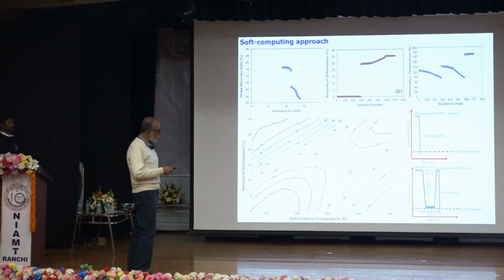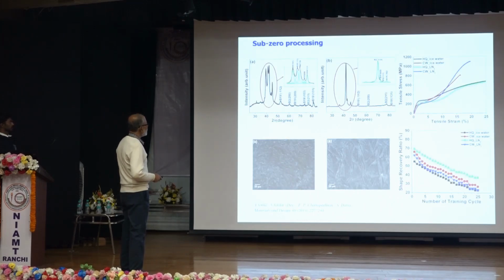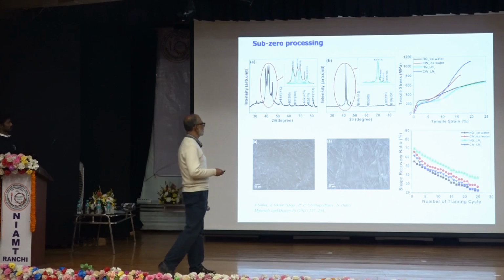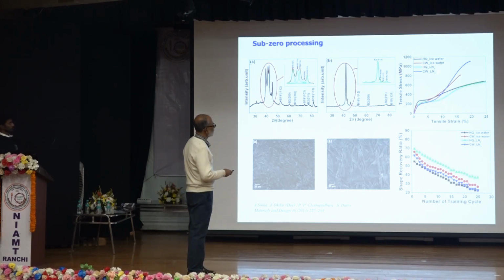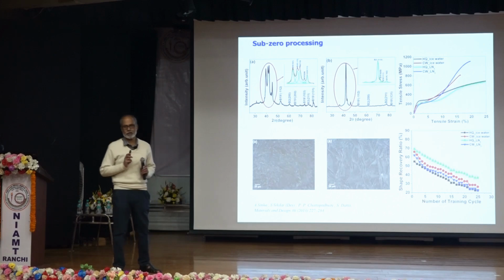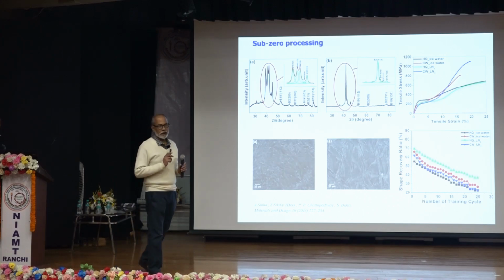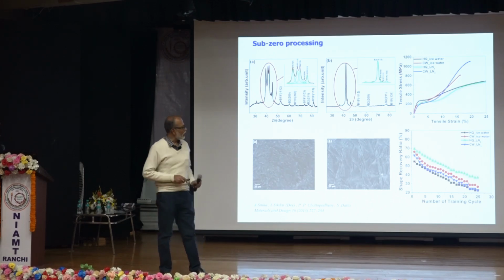So from that, we thought of doing some experiment at lower temperature. We homogenized the sample and just quenched it in liquid nitrogen without cold deformation. Forget about others. Look at this slide. This is recovery behavior. You can see this particular sample, which is homogenized at 900 degrees centigrade and quenched in liquid nitrogen, offered about 10% recovery strain, which is the highest so far reported in literature. In most of the literature, the recoverable strain is around 7%, 8%. But this particular treatment, which had not been conducted earlier, offered us a 10% recoverable strain.